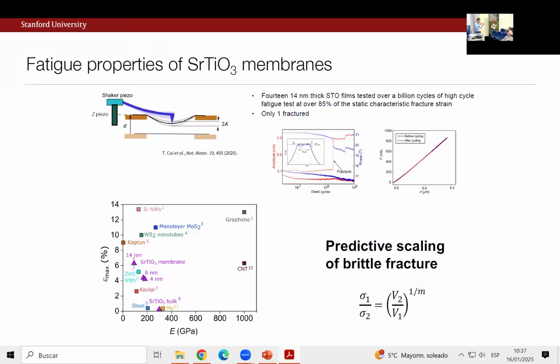So I told you before that if we had a thick membrane or a single crystal, the fracture occurs below 1% strain. But we can stretch this thing up to, in that case, 8–9% strain. As far as I understand, to leading order, the issue is simply that our membranes are much thinner, or there's much less net volume, and there's a simple relationship that governs the fracture stress statistically in terms of their volume ratio. Again, it involves a sharpness parameter. So it's useful in the sense that it can give you a fairly easy way to test and figure out what is the available range of strains that you might be able to encounter in an experiment.